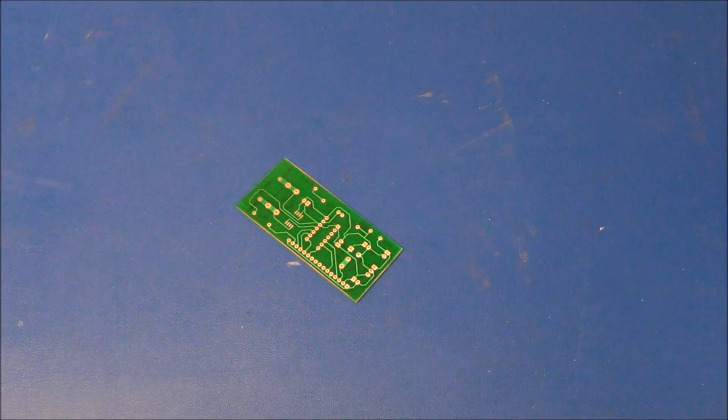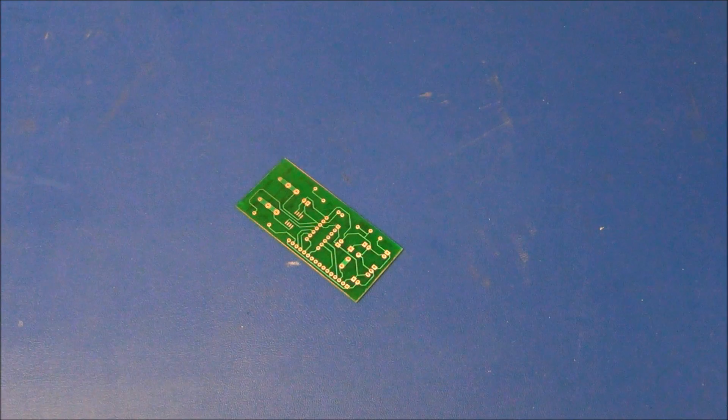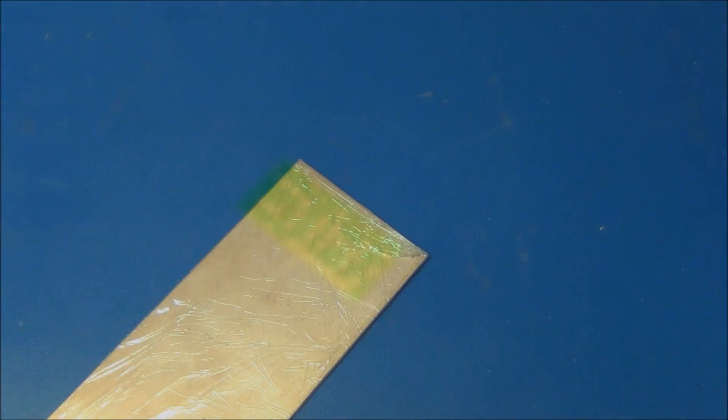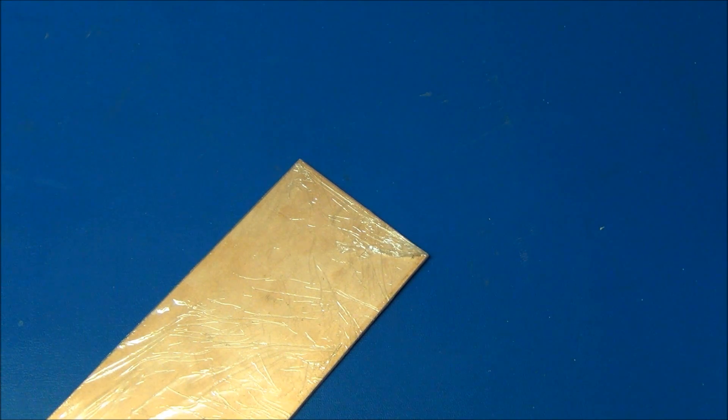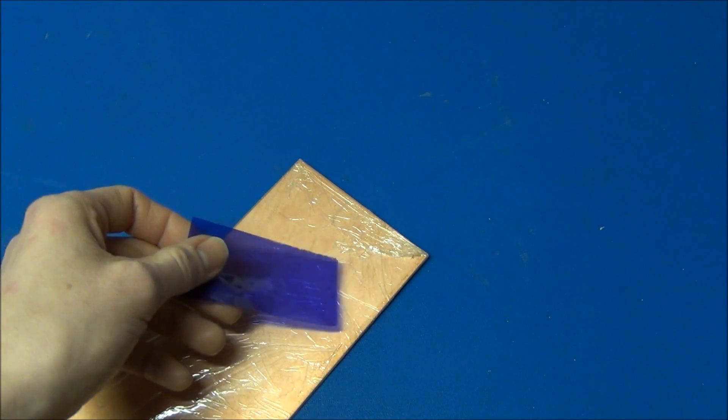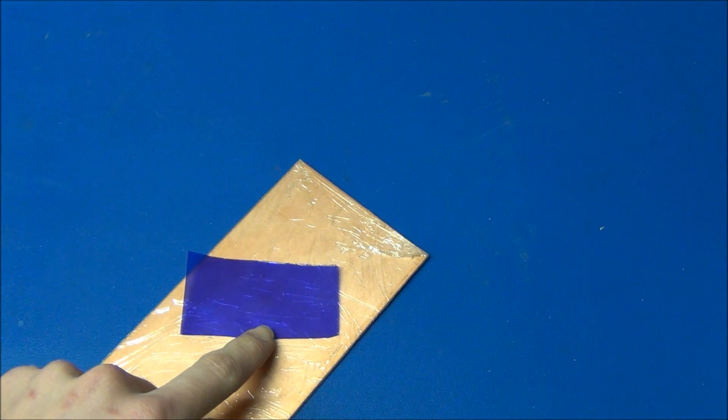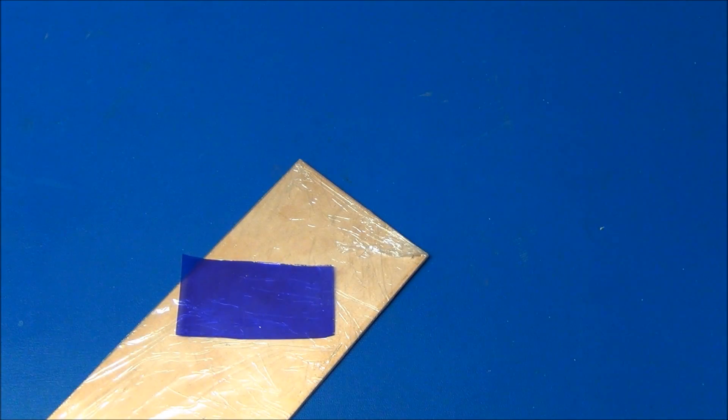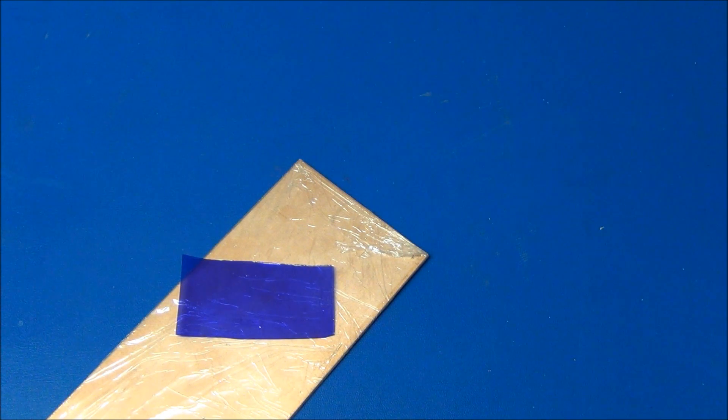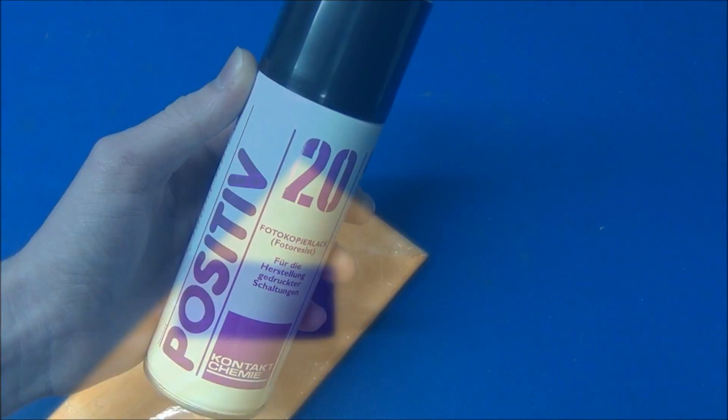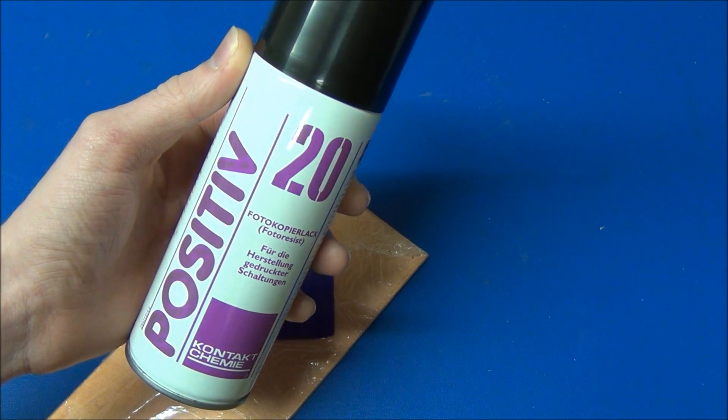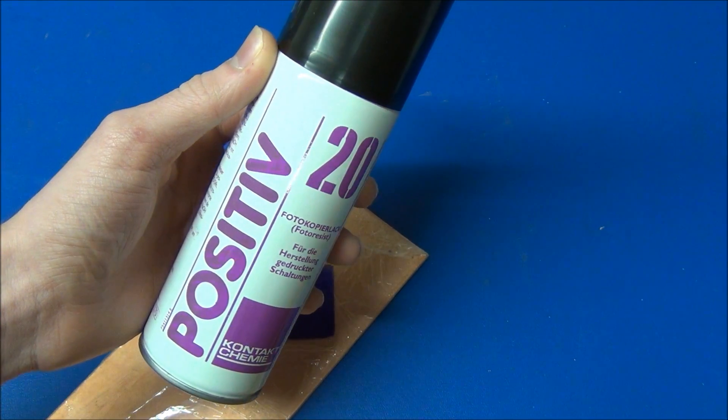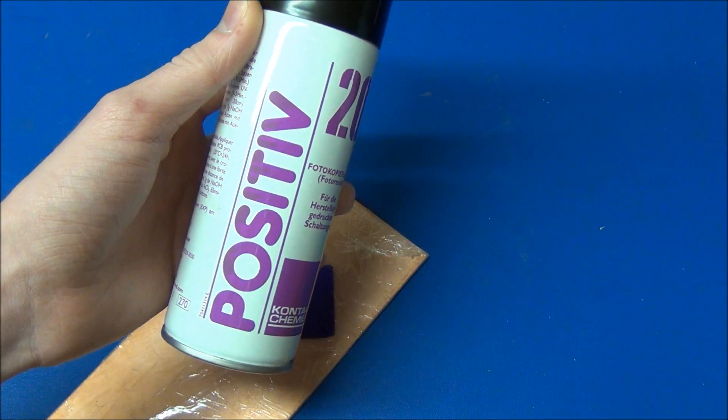For the UV exposure method you will need a little bit more, but it should be easy to pick that up. You will need some raw circuit board. This can be pre-coated with photoresist or you will have to coat it yourself. I like using this dry film photoresist. This is a negative resist, where the ones you buy pre-coated are usually positive resists. You can also use a spray resist to cover your boards. This is also a positive resist.